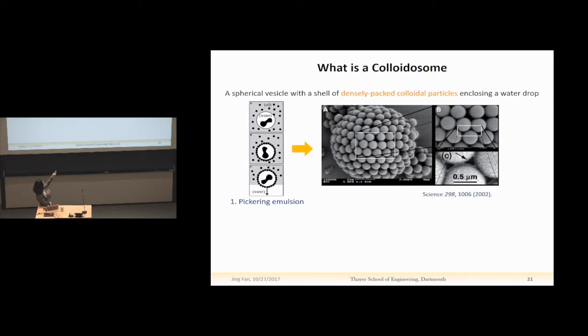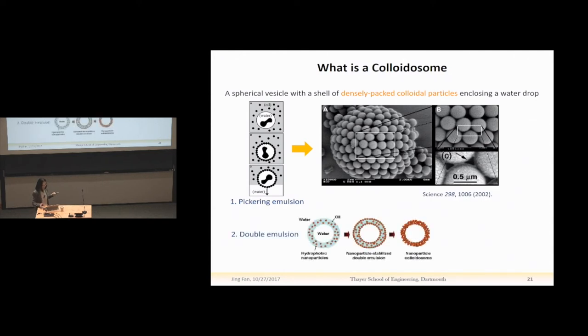And this SEM shows the colloidosome very clearly. In this case, this colloidosome consists of one layer of colloidal particles. But we can clearly see the interstitial pores among these particles. And later, people developed a new approach using double emulsion drops as the template to form colloidosomes.